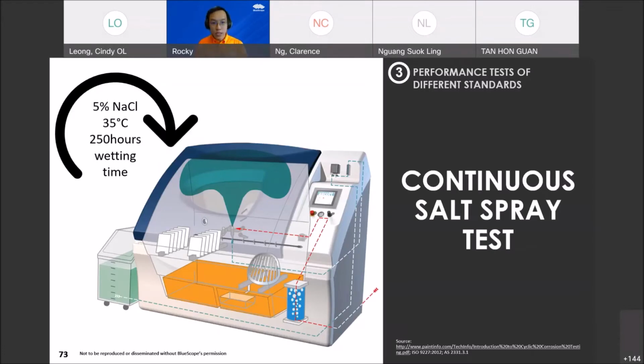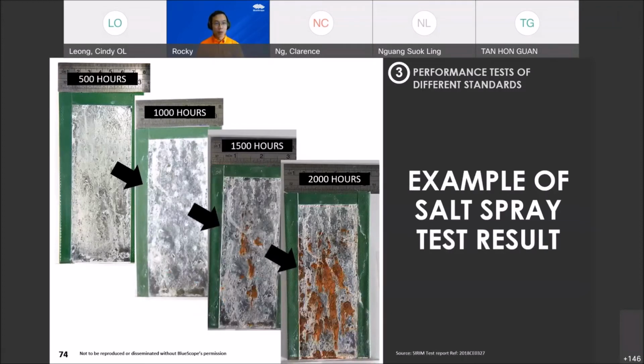But generally, this is super general, this is what the salt spray test condition would be. When they spray out the solution from the nozzle, it contains 5% NaCl, which is 5% salt. So meaning the solution sprayed out from the nozzle is a 5% solution, right? And the temperature of the chamber itself will be 35 degrees Celsius. And it will be 250 hours of wetting hour, meaning the spray would go on for 250 hours. And if you want, for example, 1,000 hours or 500 hours or 2,000 hours, then they will do that continuously, right? And you might yield results like this: 500, 1,000, 1,500, and 2,000. So of course it gets more corroded over time. Okay, but it yields the corrosion result.